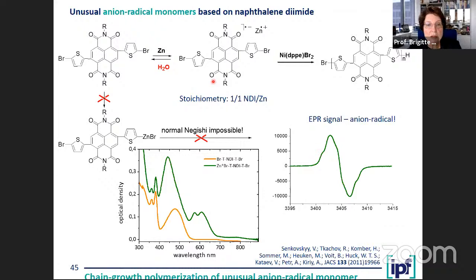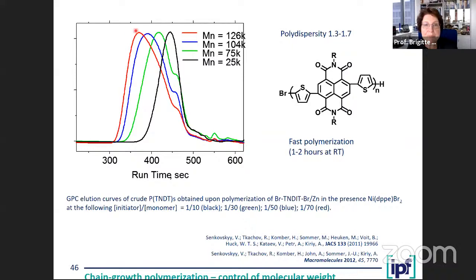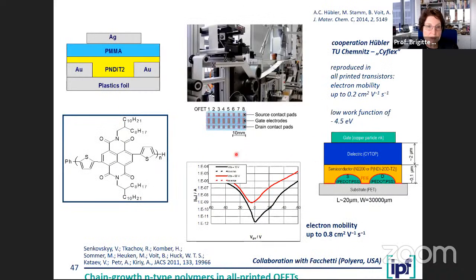We developed this also for our specific chain growth condensation process, and developed a specific mechanism which goes through a radical anion, but it works really well. So we can make material which follow also a controlled mechanism where we can control the molecular weight relatively nicely. And importantly, the material can be produced in a procedure which takes place at room temperature, which leads to very less defects and in very short time. So by that, we were able to use the material directly in such a printing machine to make some of those OFET materials, which show quite good electron mobility.